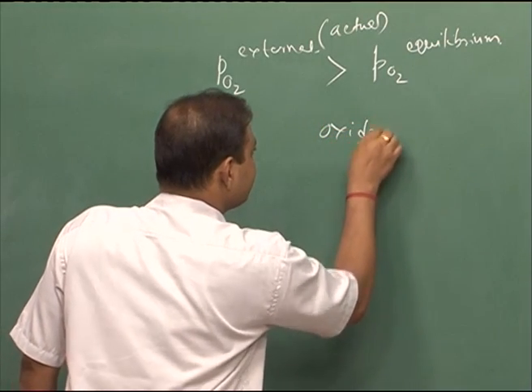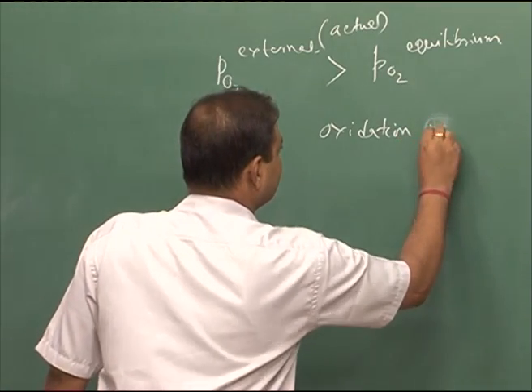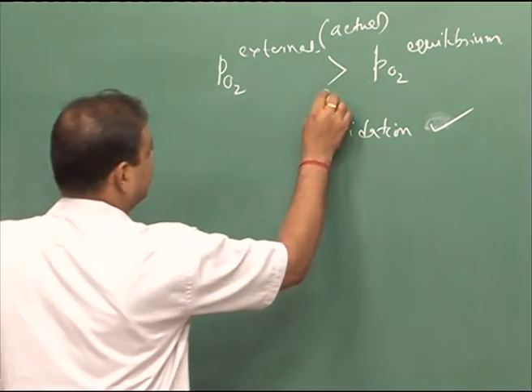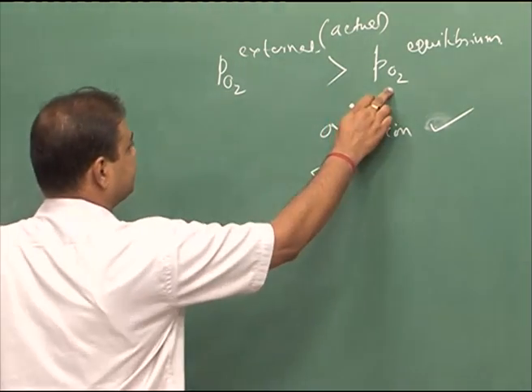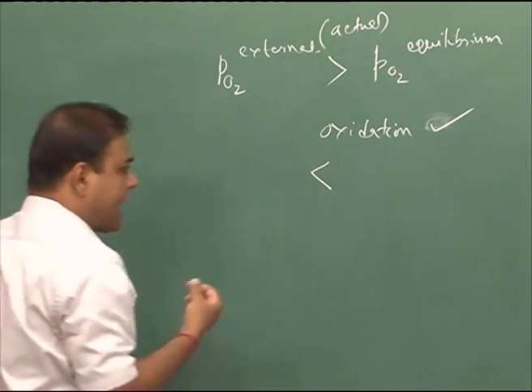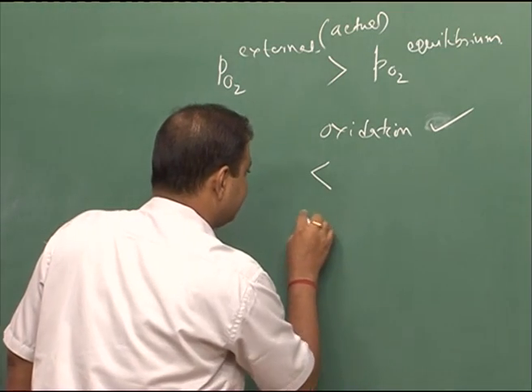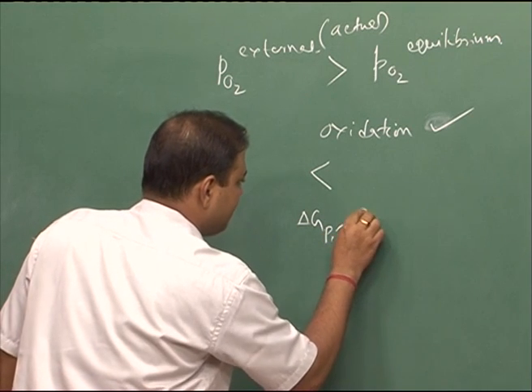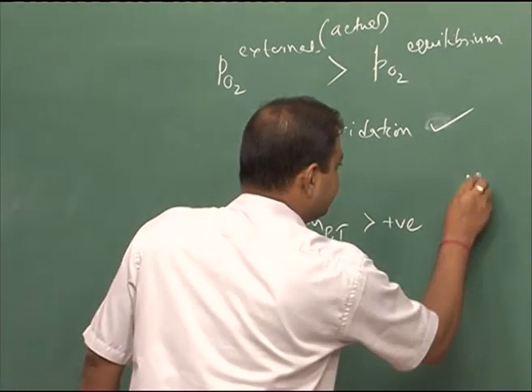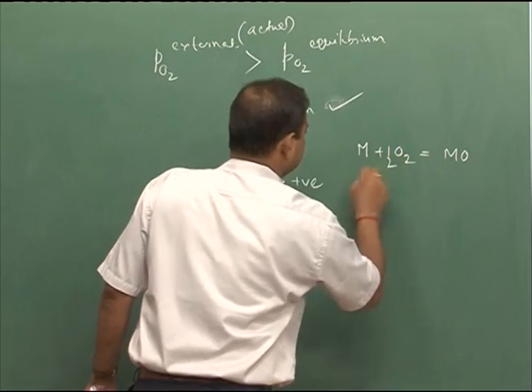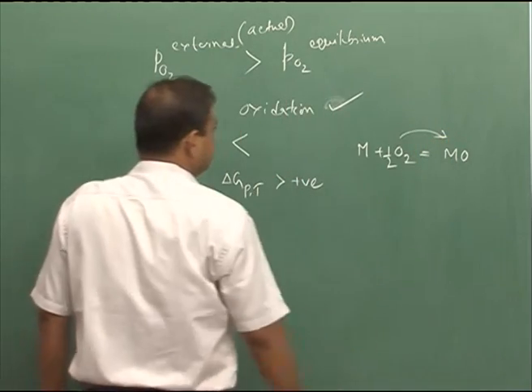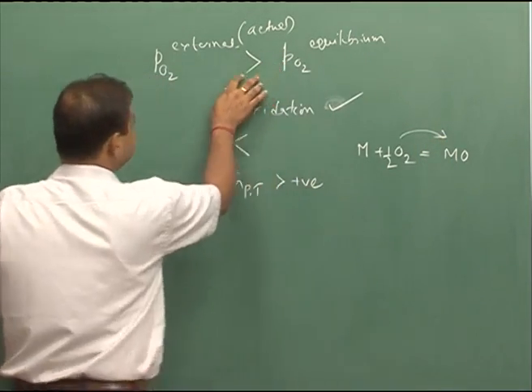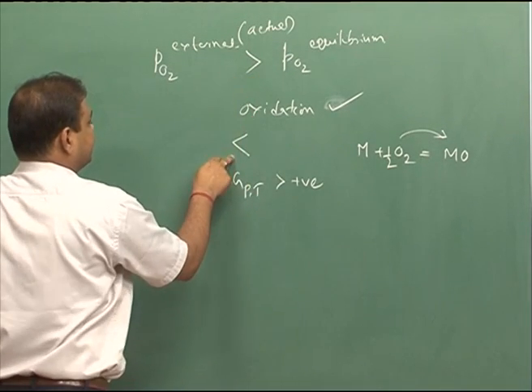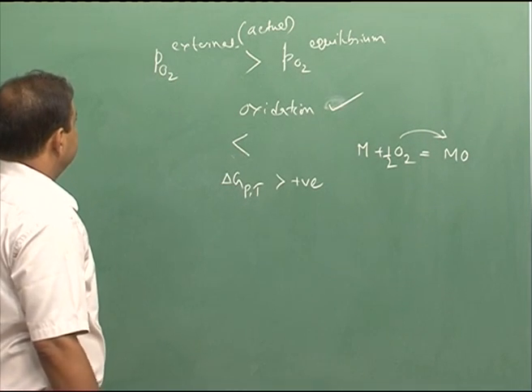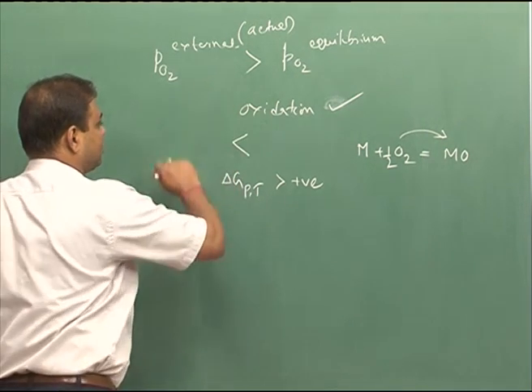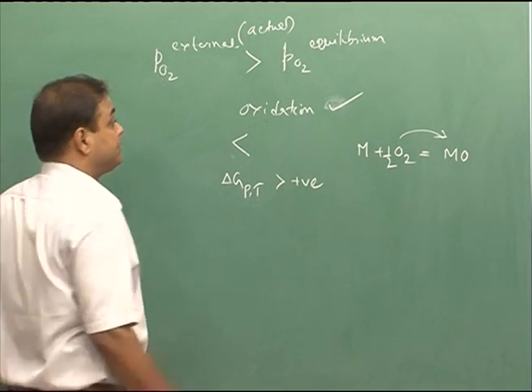So, oxidation would be possible for that metal. But if this is less than this, that case oxidation will not happen, because del G P T at that condition is positive for this reaction. So, if it has to go this way, del G P T should be negative, which is possible in this situation, so oxidation would happen. And if the situation is like this, where the partial pressure of oxygen in contact with the metal is less than the partial pressure of oxygen needed to reach equilibrium at that particular temperature T.